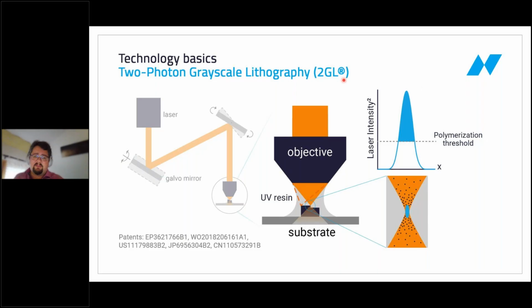So we're briefly going back to the sketch of how the technology works. Again, we have the galvo mirrors, the microscope objective, and the light is focused into the UV resin droplet. And I mentioned that there's a certain region in which we go above the two-photon threshold and certain regions where we don't cross it. So there's a region where we get two-photon polymerization and everywhere outside we don't. You can visualize this by plotting schematically the laser intensity. Actually, you have to plot laser intensity squared because it's a nonlinear process. We're actually dependent on the intensity squared. But either way, at some point this will be above the threshold, and at some other point it will be below the threshold. Again, just one direction picked at random here.